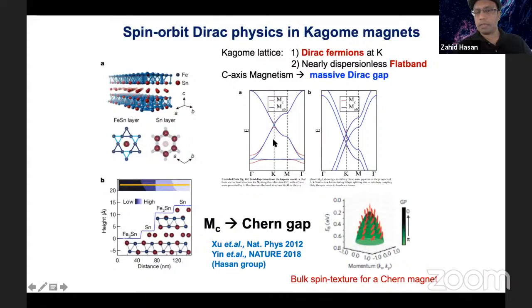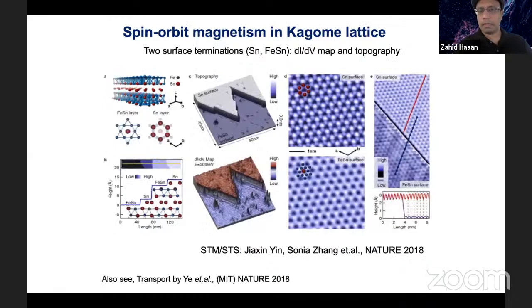Some of the Kagome magnets have out-of-plane magnetic moments, and the out-of-plane magnetic moment could introduce a Chern gap. So we showed that this happens in a number of compounds, first with this iron tin compound. This compound was also studied by a group at MIT using transport primarily. We are probing this with STM. We wanted to see what the electronic structure is, which is difficult to do with ARPES. ARPES will pick up signal from the top few layers. So we wanted to create a contrast by layer in the electronic structure, Kagome layer and non-Kagome layer. This STM topography allows us to do that.